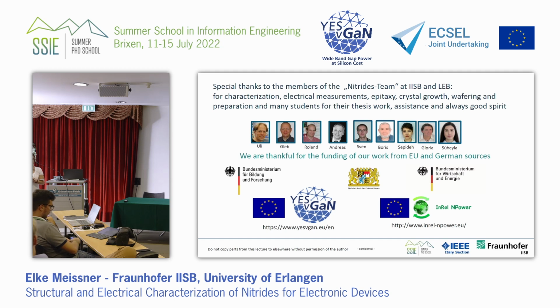Actually, there is a paper from a former student of mine, Michael Knetzger. He has calculated surface energy because of these V-pits. The question was also why gallium nitride forms a V-pit with the inclined sidewalls and not the hexagonal prism. It's a geometrical consideration which comes to the point that there is this nucleation energy with a supersaturation needed to nucleate the sidewalls. But you cannot really distinguish if you have both at once and you find the impurities inside the V-pit. You cannot say what is chicken and what is egg.